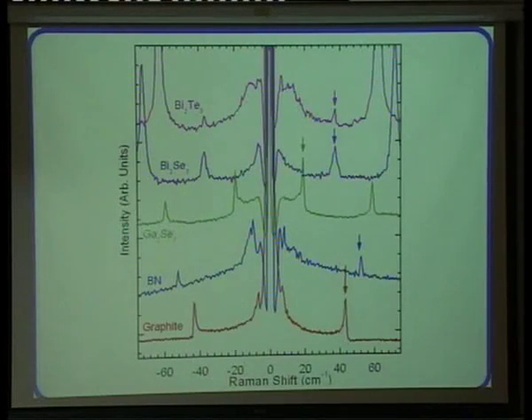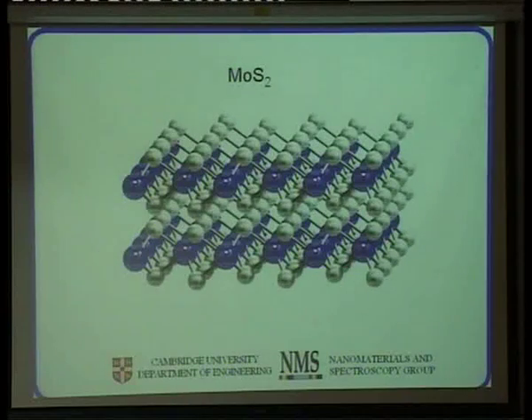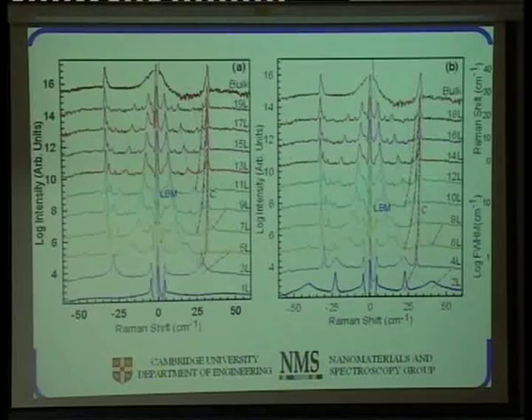And if we want to go more in detail, in the case of MoS2, and I don't want to bore you to death, but essentially all these modes are now accessible, and there are two main categories of mode. One is the C mode, so the shear, and the other one is called the layer breathing mode, the planes moving one with respect to the other like this. The one is the shear, the C mode, and the other one is this mode, okay? So these two modes are at very low frequencies. They've all been studied, and okay, if you do Raman, it's interesting. If you don't, it's not, but whatever.